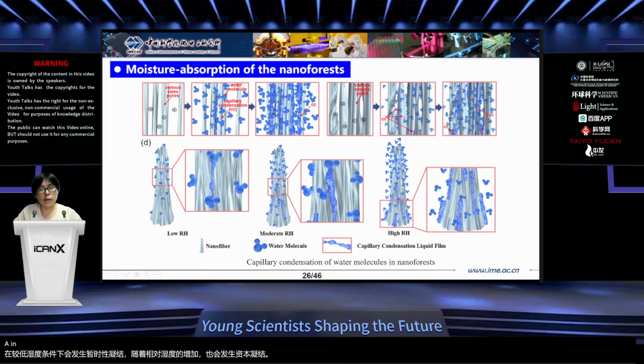in the larger pores. In addition, due to the one-dimensional order of the morphology distribution of the nanoforests, and due to their hydrophilicity, the condensed water molecule layer can transfer along the vertical structure downwards to the bottom of the nanoforests and converge at the metal electrode positions. Therefore, the effective dielectric constant further increases, which in turn enhances the sensitivity of the device.